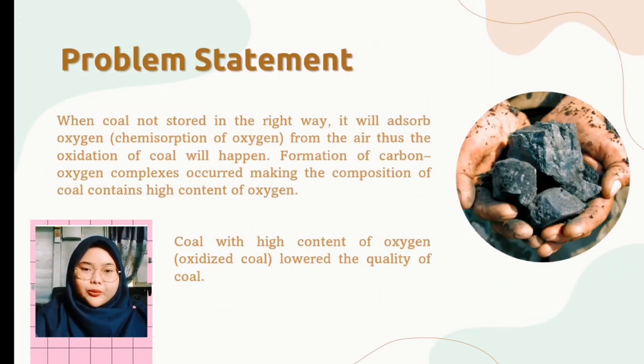Next is the problem statement. When coal is not stored in the right way, it will adsorb oxygen, also known as chemisorption of oxygen, from the air. Thus, the oxidation of coal will happen. During the adsorption of oxygen, formation of carbon-oxygen complexes occurs, making the composition of coal contain a high content of oxygen. Coal with high content of oxygen, or called oxidized coal, lowers the quality of coal.